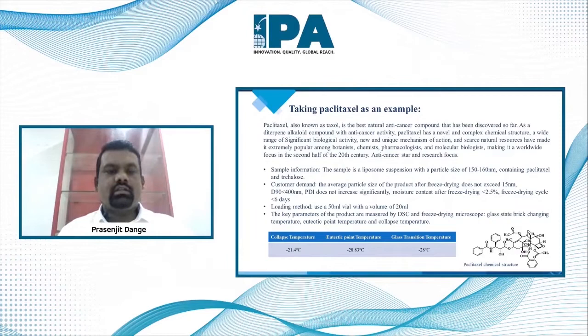Now we used a 50 ml vial in this case with a 20 ml fill volume, and with the available methods and all these parameters, we could determine the temperatures, where you can see the collapse temperature is minus 21.4, the eutectic point is minus 28.83, and the glass transition temperature was minus 28. With this, we adapted the cycle. Can you go to the next slide?